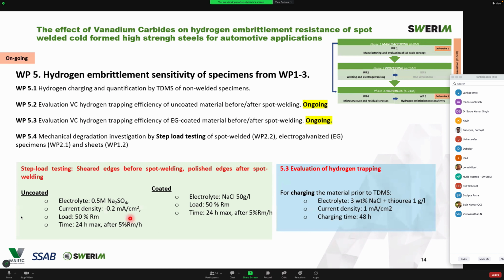Yes, so we have the electrolytes here. For the step load testing, we use 0.5 molar sodium sulfate with this current density here. For the uncoated material and for the coated material, that's the electrogalvanized material with zinc, we use sodium chloride. And when it comes to the charging prior to TDS, we used sodium chloride plus a recombination poison, that's thiourea in this case, 1 gram per liter, with the current densities as you can see here.